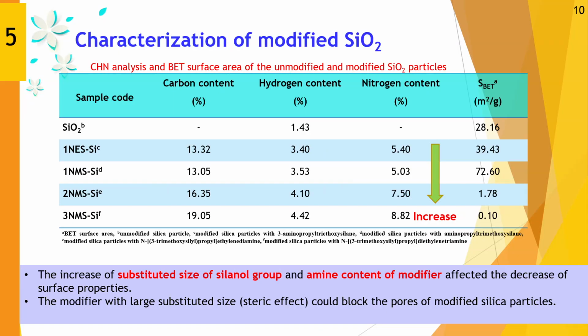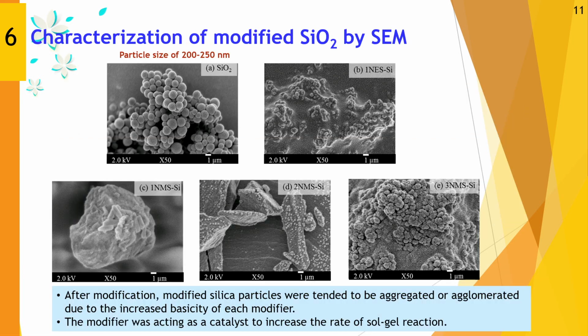After modification, we found that the carbon content, hydrogen content, and nitrogen content of the modified silica particles tend to increase. The increase of the substituted size of the silanol group and the amine of the modifier affected the decrease of the surface properties. The modifier with large substituted size could block the pores of the modified silica particles.